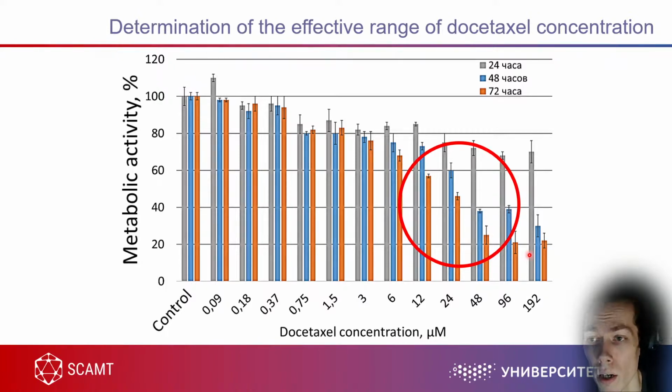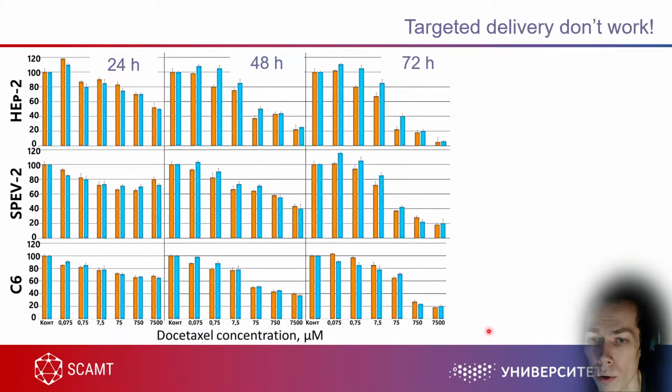But on the surface of some nanoparticles, there are no molecules because the concentration is so low. And because of this, some of the cells receive nanoparticles with no drug, and these cells will survive. And because of the survival rate, we see some increase in viability of the cells.